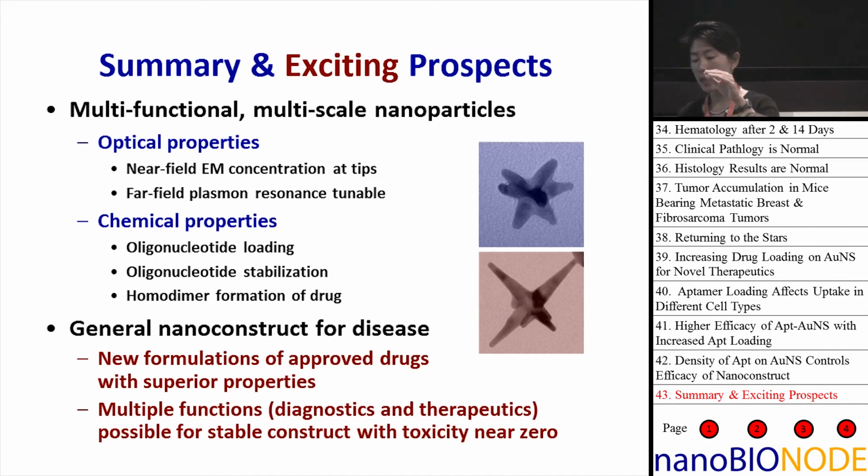He found that different shapes could have different penetrations compared to ones that were close to the blood vessel. So we don't know that, but my suspicion is that we can actually penetrate pretty far, based on some other results that we've done in three-dimensional cell cultures, these human tumor neurospheres. The star shape can penetrate to the center while the spheres stay on the outside. But that's the best evidence that we have for that.